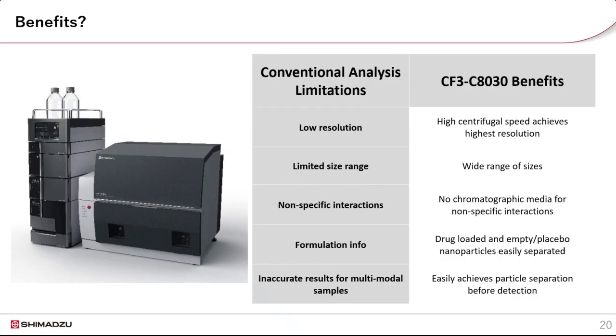The high centrifugal speed assists with achieving higher resolution between particles of closely similar sizes. The size range is wider than other technologies, offering from low nanometer to multi-micron separation capability. There is no chromatographic media, as in SEC or HDC, for non-specific interactions to take place. Drug-loaded and placebo or empty liposomes or nanoparticles can easily be distinguished based on the difference in their masses. And finally, even if the sample has nanoparticle populations of a variety of sizes, separation will consistently and effectively be achieved, unlike DLS.